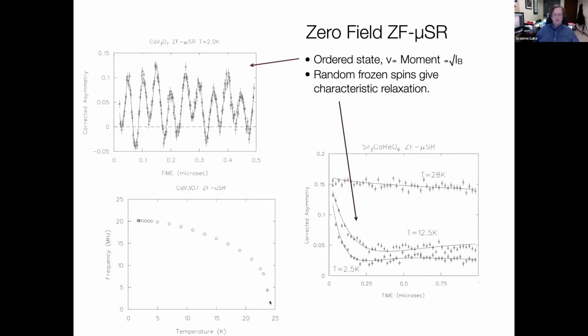But because we're not a diffraction technique, we implant the muons and they stay at rest. We don't need to have long range order to sense the internal magnetic fields ordering. So for example, in materials which are glassy, we get a characteristic relaxation function, and you can study glassy behavior just as well as long range ordered materials. So sometimes that part of it can be more powerful than a diffraction scattering experiment. Of course, we lose information about correlation lengths, so nothing ever comes for free.